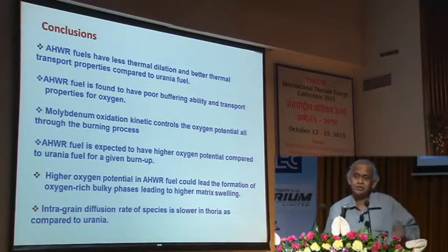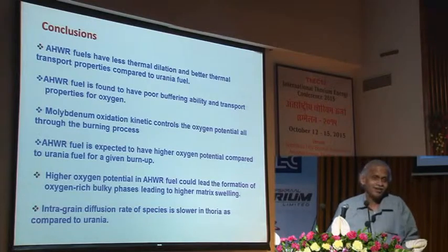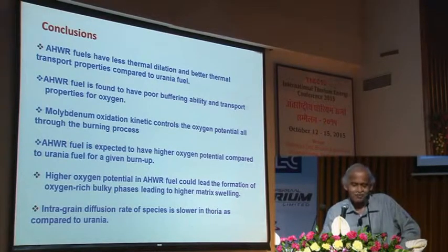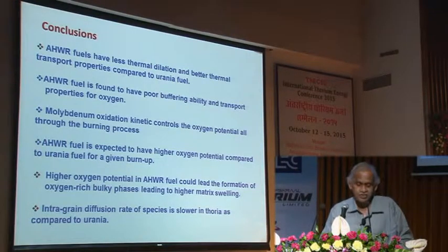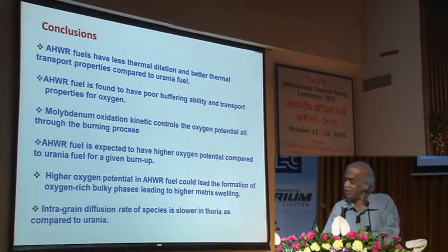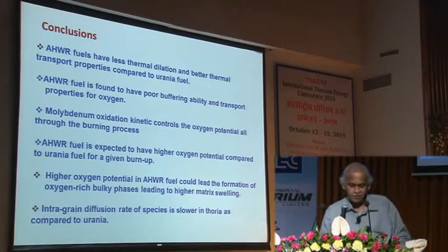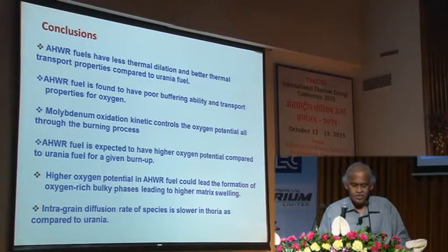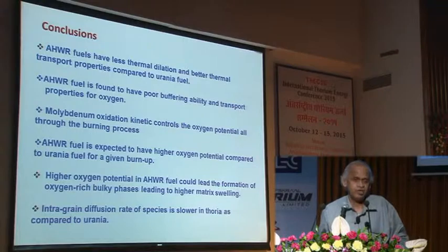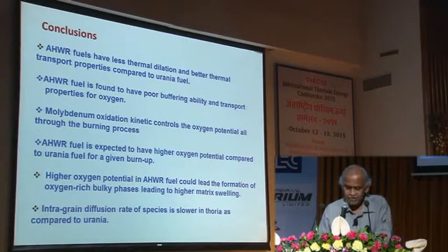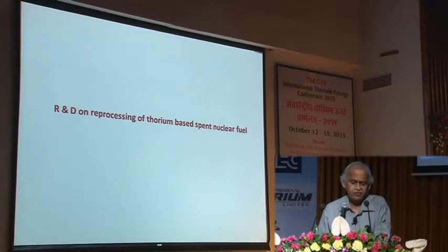I hope Vijayan Saab would agree with my observation on chemistry-related points, because he is the architect for AHWR. There should not be discussion. And AHWR fuel is found to have a poor buffering ability and transport properties for oxygen. Molybdenum oxidation kinetics controls the oxygen potential, and I need not read it, it is there already. Intragrain diffusion rate of species is lower in thorium as compared to uranium. All these facts have been taken into consideration before designing and fabricating the fuel for AHWR.